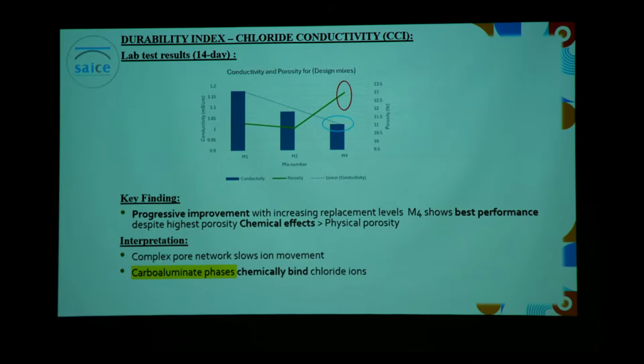And then we ended off with our chloride conductivity index, where we saw that there was a progressive improvement when we were replacing our study materials in our concrete mixes. So what we found here with the M4, it showed the best performance in terms of chloride conductivity index, which means it was resisting our chloride conductivity.